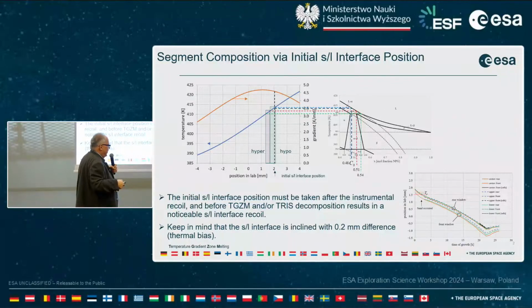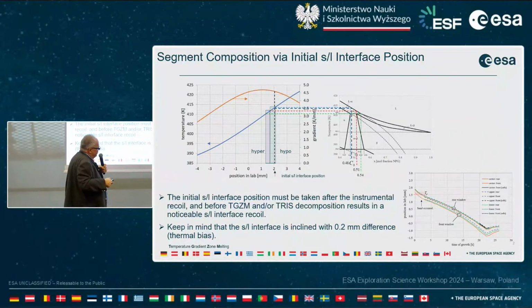And what we found out is another problem. We are not sure whether this is a consequence of the material, or whether this really depends on peritectic coupled growth, that we have a very, very long recoil. And even if we reach the first part where we then have dendrites, peritectic coupled growth, the solid-liquid interface never reaches a stable situation. Steady state was never reached.